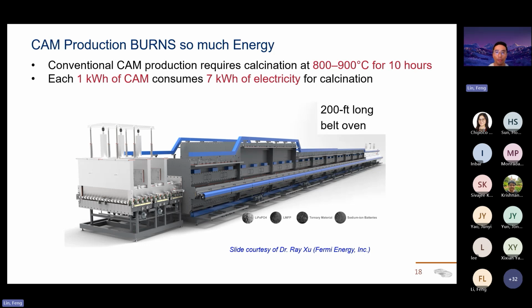We have started looking into some additional factors, which is the production. Conventional cathode active materials production requires calcination, and this refers mostly to layered cathodes, at 800 to 900 degrees C, usually for an extensive number of hours. As a rough estimate, each 1 kilowatt hour of cathode active materials will consume 7 kilowatt hours of electricity for calcination. That contributes to the cost of making and decreases the profit margin for the manufacturers.